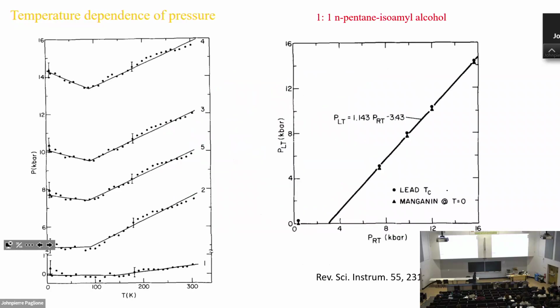Okay, talking about the change of the pressure. This is a study from Los Alamos. It's already 40 years ago. So they used 1-to-1 n-pentane-isoamyl alcohol. That's about this pressure medium. And they studied how the pressure changes. There's a linear relation that they found. So the pressure does decrease in this type of pressure cell. The diamond anvil cell is opposite. In a diamond anvil cell, typically the pressure will increase as you cool down the temperature. So you have to keep that in mind.